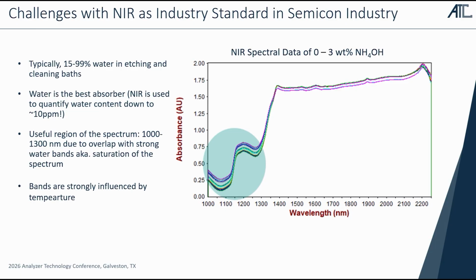It helps us if we want to do very low moisture content. That would be great, right? If water content is low, then we can use NIR spectroscopy, but for a lot of aqueous systems, it's just overlapped. And it's still being used. People still use NIR for etching bath control, but I want to show that an indirect measurement is not truly what we want to do. We want to use specific bands and do a direct approach, and not just by some background shifts or whatnot. And also NIR spectroscopy, if you have water in it, is very temperature dependent.